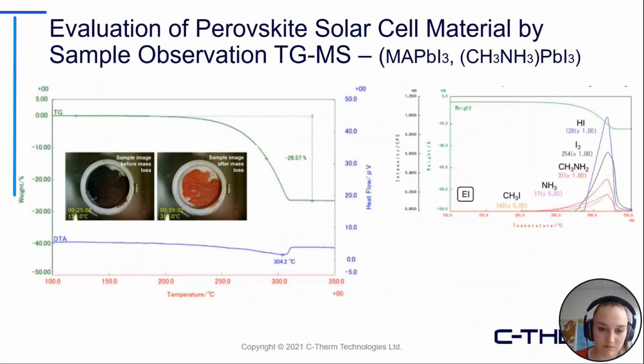So this is just an image actually, but you can see that before the mass loss, the sample was black. After the mass loss, the sample actually is red. So the gases evolved from this mass loss were determined on the right. They're determined to be hydrogen iodide, iodine, and methylamine. Now there are a couple others, but those would be the main evolved gases.